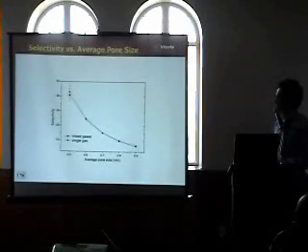So we studied the effect of average pore size on permeances of gases and selectivity. As the average pore size decreases, the selectivity goes up. That's again because of the percolation effect. When we use a smaller average pore size, argon cannot diffuse through some of the pores. So the permeance of argon starts decreasing more than helium, so the selectivity goes higher and higher.